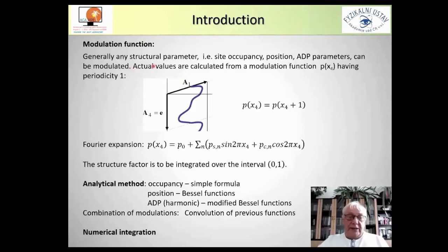Generally, any structural parameter, this means site occupancy, position, ADP parameters, can be modulated. Actual values are calculated from the so-called modulation function, which has periodicity 1. This periodicity allows us to make expansion into Fourier coefficients, and these P0, PSN, PCN are parameters which are to be solved and refined during structure solution.